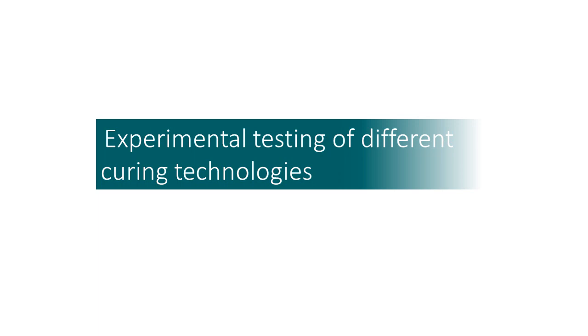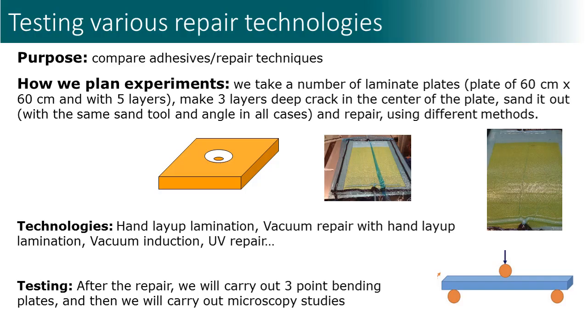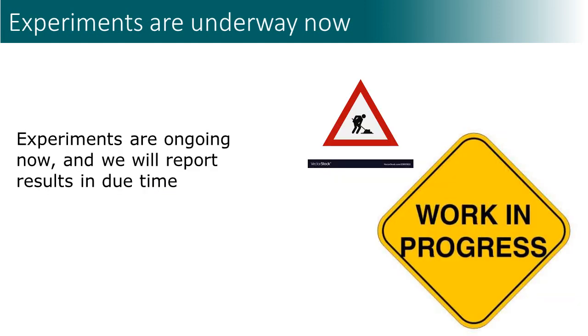The simulations and studies above gave us some hints and directions on how to improve the repair technology. We seek to compare different curing technologies experimentally. The experimental program includes the following steps. We take several laminate plates, damage them, and repair them using different technologies. The technologies to be tested are hand layup lamination, vacuum repair, using ultraviolet curing, and others. The samples will be tested, and the results will be analyzed and presented. The experiments are still underway now, and we will report results in due time.